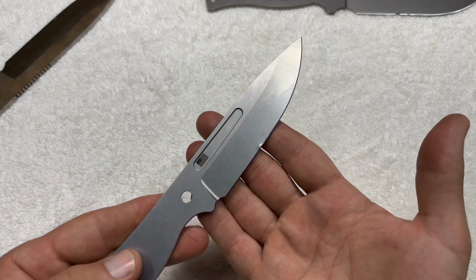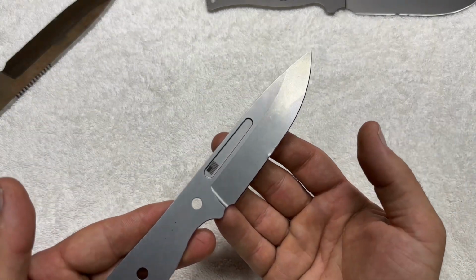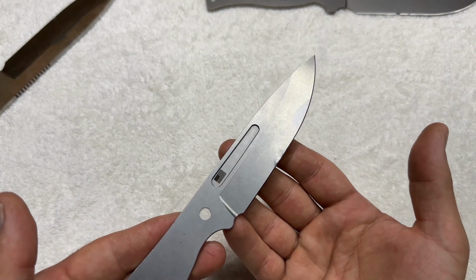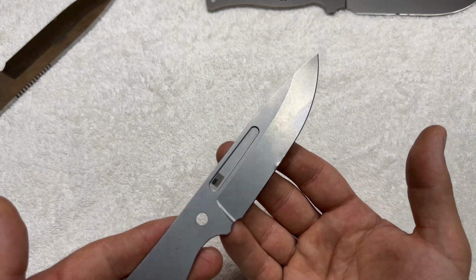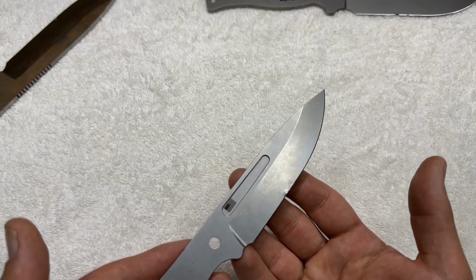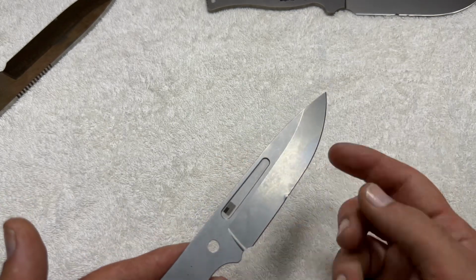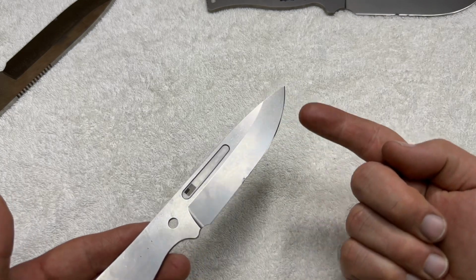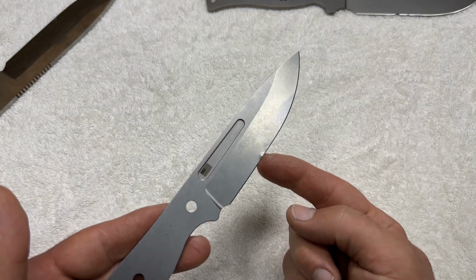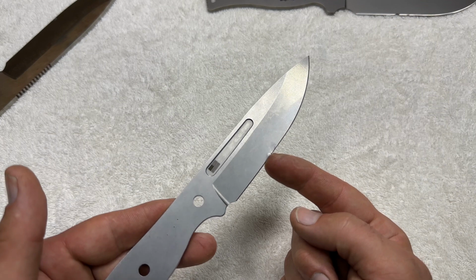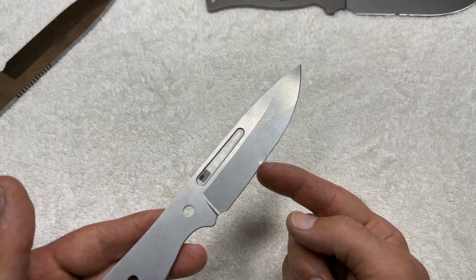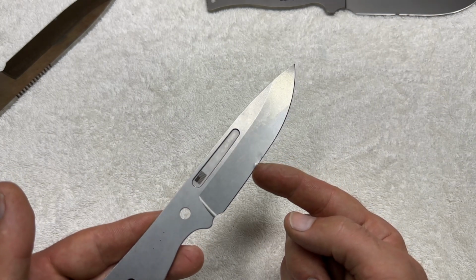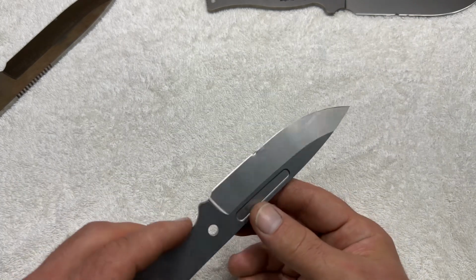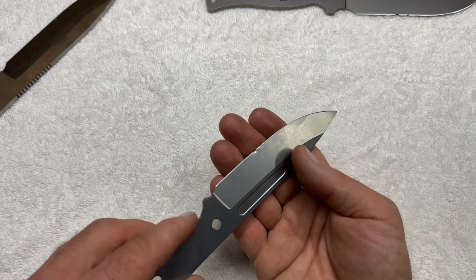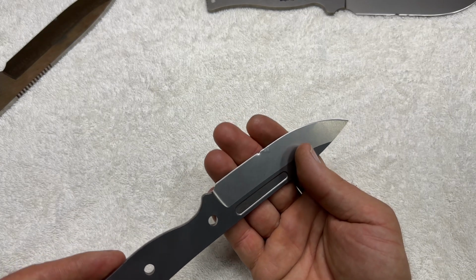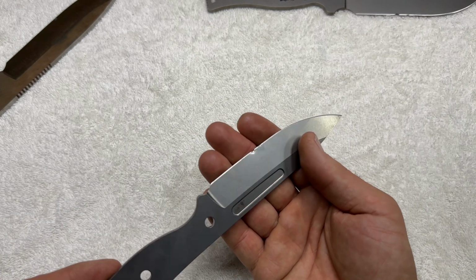I should mention, this is also why I never made a Scandi in 3V. When you have a high chromium, high vanadium steel, it has a very high abrasion resistance, and with a Scandi style knife, you're grinding the whole daggone bevel that's huge in a Scandi. So if you have this sort of apex damage in these fringe circumstances, it's a bear to grind all that back on a large cutting edge like that. There's actually a lot of high quality stainless steels that would handle the side loading in a Scandi geometry a lot better than something like 3V.